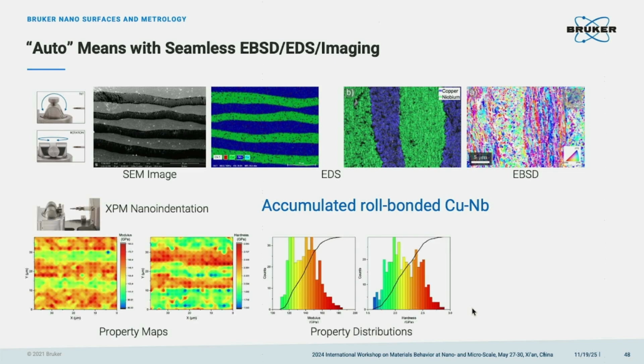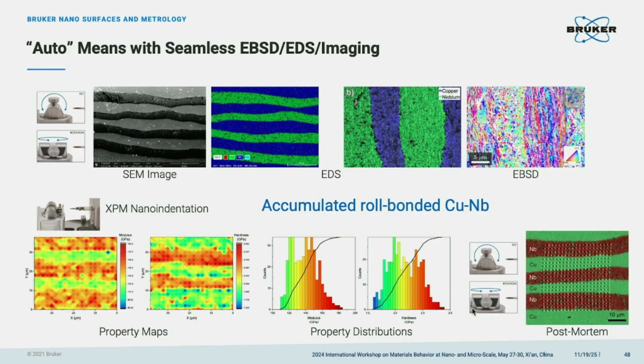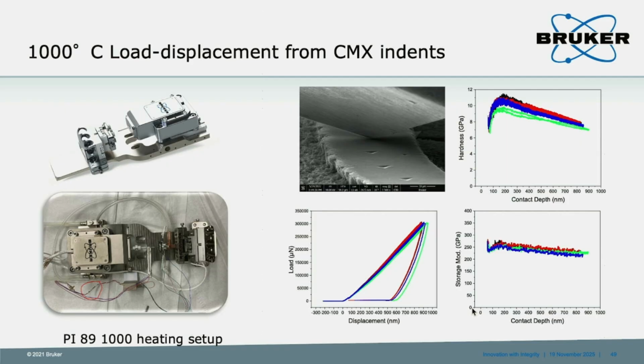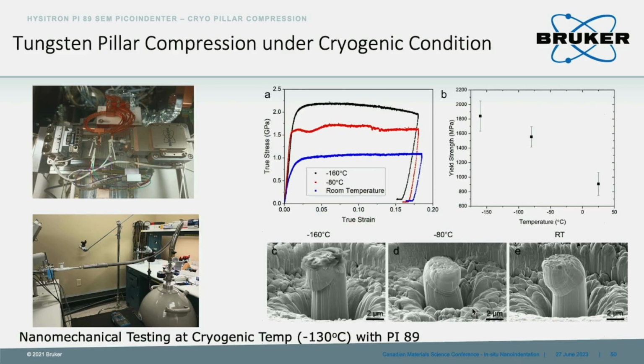Then we can do the EBSD EDS mapping with the mechanical testing. That's what we call the one chamber solution. And we also can do high temperature measurement inside of the SEM. This is silicon carbide within 1,000 degrees Celsius, and we are doing the indentation on silicon carbide. Cryogenic inside of SEM, so we can do minus 160 degrees Celsius for the pillar compression.